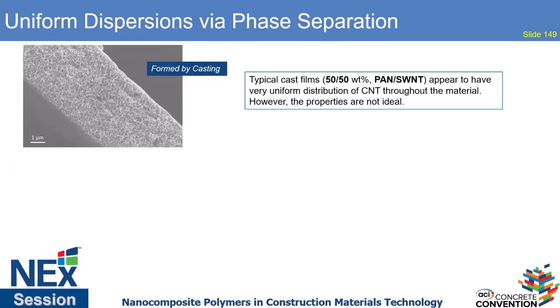So this would be a cross-section of a composite material containing about 50 by weight nanotubes in a polymer. So this polymer is polyacrylonitrile, which is a precursor for carbon materials, single-wall nanotubes. And if you look at this cross-section, we've done a pretty good job by all standards of making sure we've dispersed these nanomaterials. So you can see it's very uniform across the cross-section, even though we have a large amount of nanotubes.